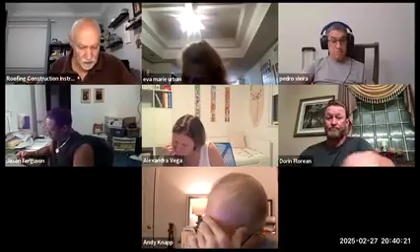Then one, two, three more paragraphs down gives you the thicknesses. PVC sheets are produced in 30, 36, 45, 60, 72, and 90 mils. Then NRCA recommends designing and specifying sheets nominally 45 mils for a conventional single ply roof system. I think it's too thin. But anyway. Then on 218, the product standard, on the first column, second paragraph, is D4434.